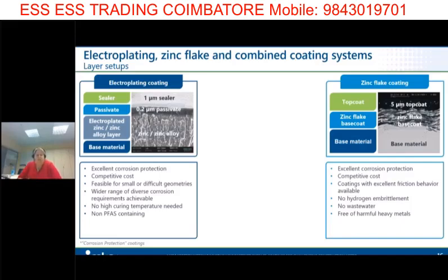The drying temperatures in case of electroplating are quite moderate, so you don't have high curing temperatures, and all the systems are non-PFAS containing. The zinc flake coatings also have excellent behavior connected to friction. As mentioned in the ISO 10683, there is no hydrogen generated, so you have no problems with internal hydrogen embrittlement. There are no rinses needed after applying these coating systems, so you have no wastewater generated, and they are free of harmful heavy metals.